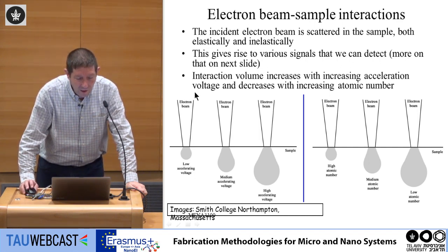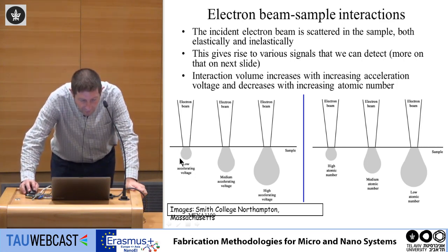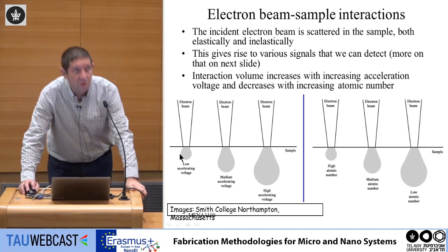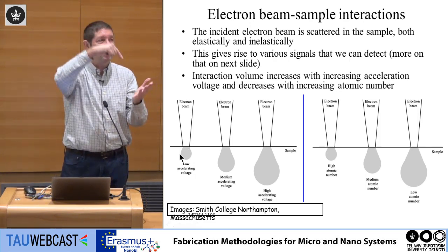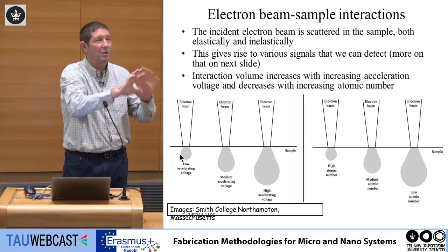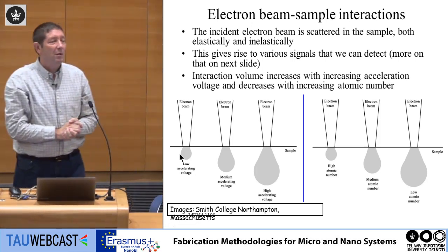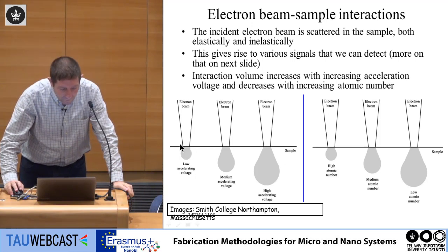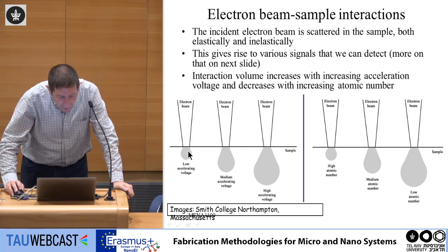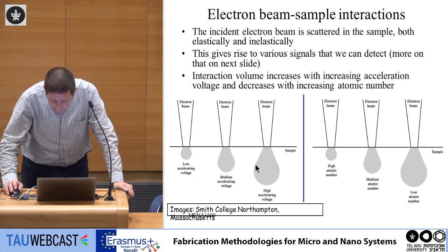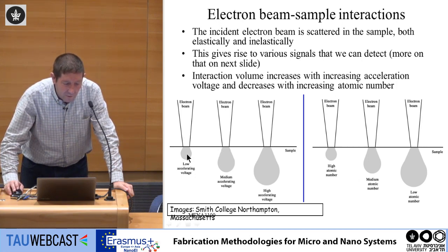And what we have here are what we call interaction volumes. Electrons go inside the material, have some collisions, and lose their energy. So at low energy, we get this collision volume, this is a moderate voltage, and this is high accelerating voltage. Now, this is as a function of the voltage.